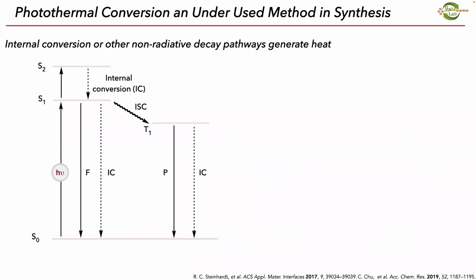So a process that we don't commonly use in synthesis in photocatalysis is internal conversion of these excited state photocatalysts. And so generally we hit these photocatalysts with light, they move into an excited state. If they don't do any chemistry, they will fluoresce or they will phosphoresce. They'll give off a photon of light. Generally what we don't want is for it to relax back down in a non-radiative fashion, in which case it gives off heat. But if we can promote that process of internal conversion or vibrational relaxation, where it only relaxes back down, we can actually generate a lot of heat.